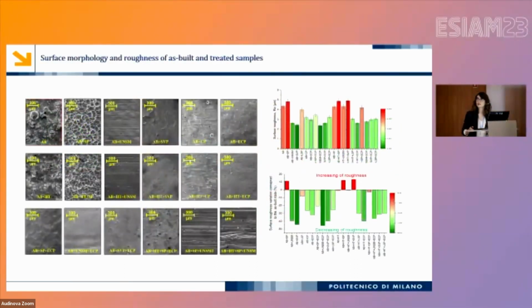And here you can see the top surface morphology of our samples after different surface treatments, starting from the very inhomogeneous and random surface roughness in the as-built condition, and then shot peening with the typical dimples that are caused by the plastic deformation induced by each single particle. Then the results for UNSM, SVP, CP, and ECP, the chemical and electrochemical polishing, which give us the smoothest surfaces, because they slightly remove the top surface layer, giving us a much smoother surface.